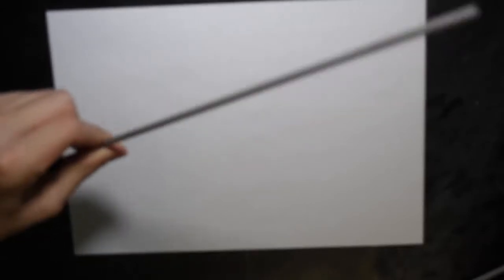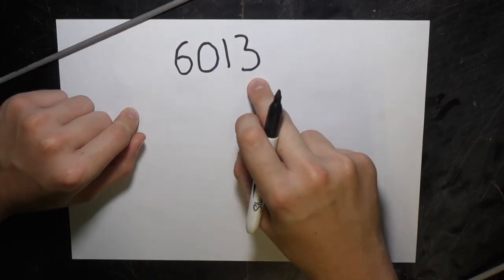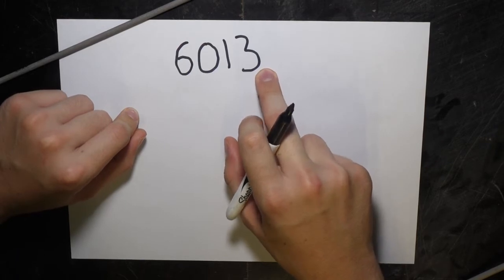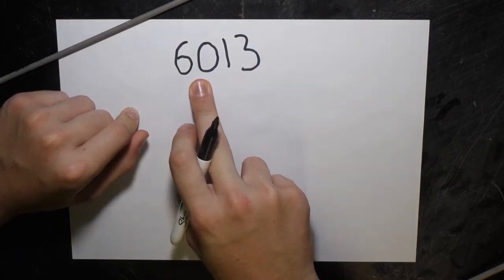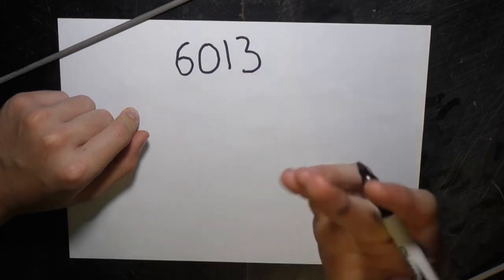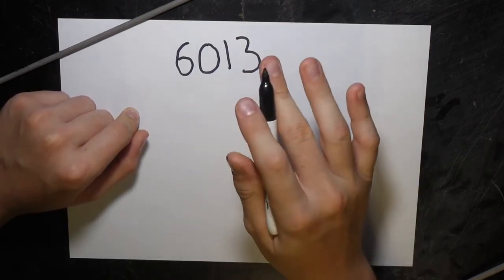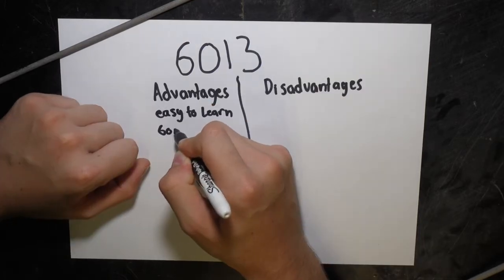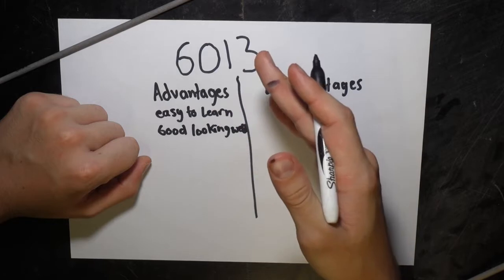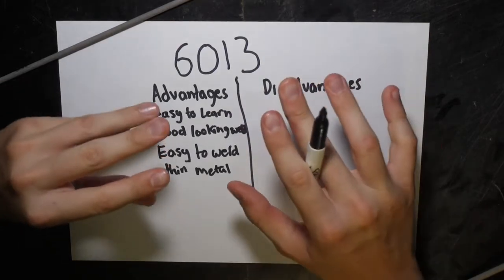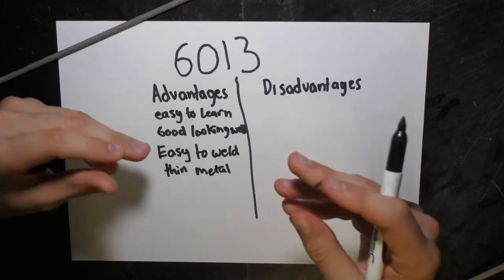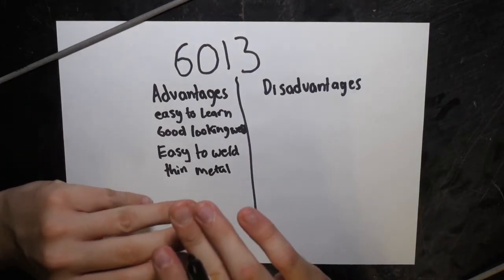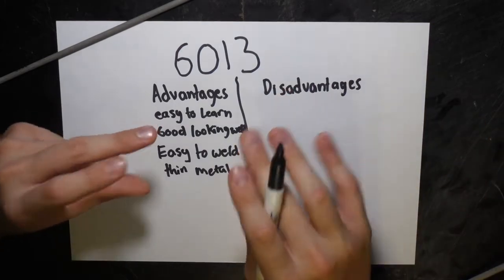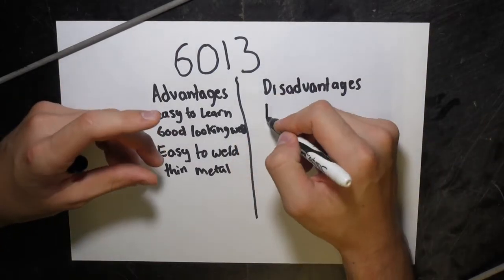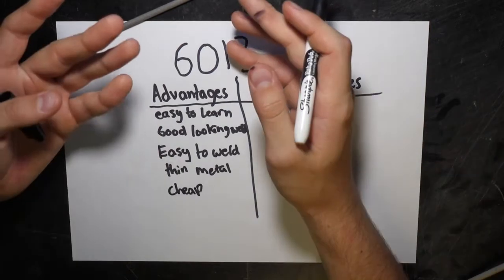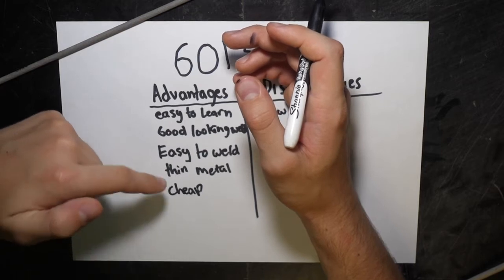First rod we'll look at, 60-13. From the numbers, we can tell this is a rod that requires at least 60,000 psi to pull apart, can be used in all positions, and whatever that means. Advantages: easy to learn, good looking welds. Easy to weld thin metal. 60-13 has a low penetration, meaning it doesn't fuse that deep through the material. This is one of its main drawbacks. Low penetration. One advantage not talked about is 60-13 is very cheap.